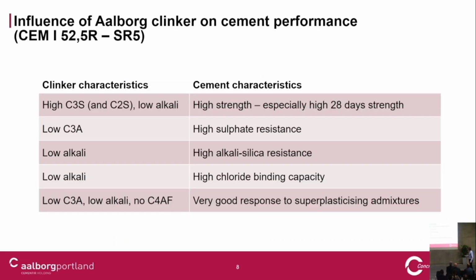So that's unique. And if you look at the composition of our clinker, and see what it does to the cement properties - cement based on this clinker will have high strengths, especially the 28-day strengths, because of the very high content of calcium silicate and the low alkali.